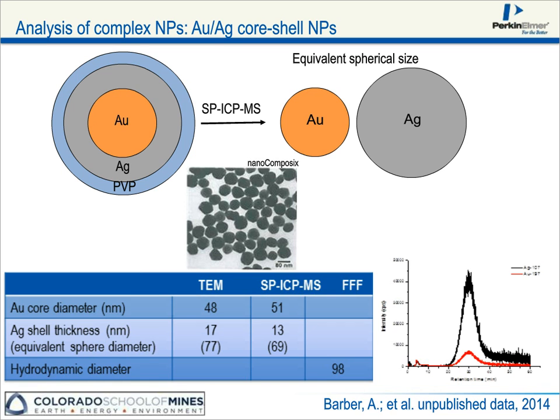This corresponds well to what the TEM sees. The TEM also doesn't really see the coating. But again, as Kevin mentioned, if you use FFF, you can get the hydrodynamic diameter, which is shown in the lower right. And that's a fractogram showing that, again, indeed, the gold signal, which is red, and the silver signal, which is black, coalesce in the FFF together. So this is not a mixture of a gold particle and a silver particle, but truly a core shell material.